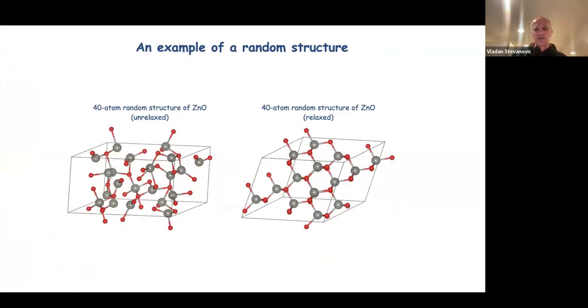So just as an illustration of how one of those random structures may look, this is a 40 atom, let's say zinc oxide random structure. We created our own random structure generator that tries to intersperse cations and anions whenever we are dealing with ionic systems like zinc oxide. So this is one example of that. And then after the relaxation, this particular one really relaxes to a supercell of the ground state wurtzite zinc oxide. So again, just an illustration, we will be generating thousands of these, doing the relaxation, and then counting how many times we end up in wurtzite or zinc blende or rock salt or the other ones.